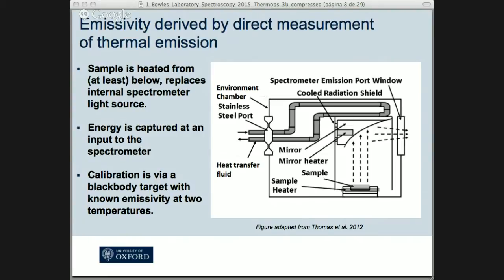And this is nice because it's as close as you can get in the lab to the way that you would do these measurements from space. But it has complications because you have to worry about all the different flux terms that are contributing to the signal the spectrometer sees. Because this is modulated by the interferometer, all the flux terms, for example the downwelling radiance term from the environment that the sample is sitting in, any reflections off the sample, that kind of stuff, will get passed through into the spectrometer. So you need a really good radiometric calibration to make sure this works effectively and gives you stable answers.